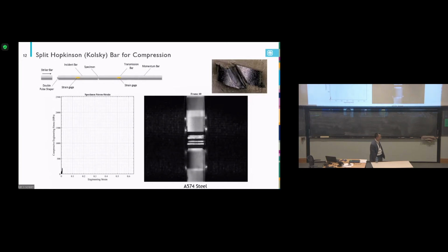We'll see how the sample breaks. And I would mention that during this split Hopkinson bar test, the duration is very, very short, generally about 200 to 300 microseconds. It's very short, very fast. So if you stand in the lab behind the bar when we fire, you only hear one sound, bang, that's it. You don't see anything.